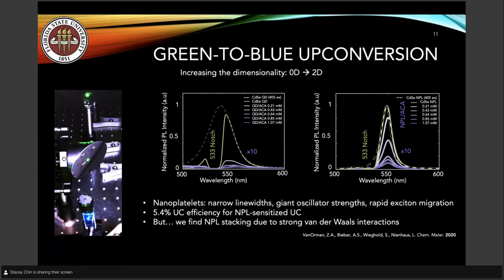We've found 5.4% upconversion efficiency at this point. However, the quantum dots are still at 16%. One of the main reasons we're seeing a reduced upconversion efficiency with the nanoplatelets is that there is stacking of the nanoplatelets due to strong van der Waals interactions. So these are extended materials, and therefore they like to stack. And there are two types of stacking. Next slide, please.